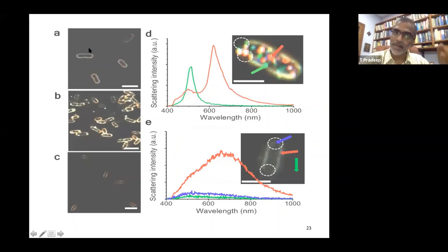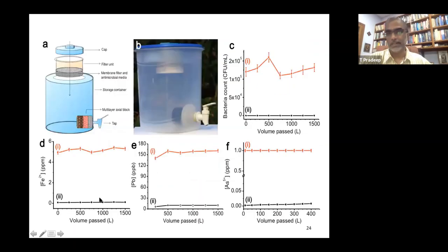But if the same number of bacteria are passed into water through our materials, they die. As you can see, lysis happens, but there is no nanoparticle inside. And that is what is shown here, several of such bacteria. What this science is telling you is that toxicity is not there with such materials. So you can make a contraption of this kind. You have materials here, pass water through and keep this water for some time, and bacteria die, of course. You have several other materials of similar kind, put them into another cartridge, pass water through, and then you can remove other contaminants as well.